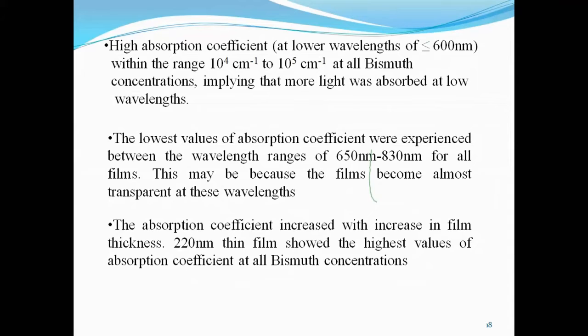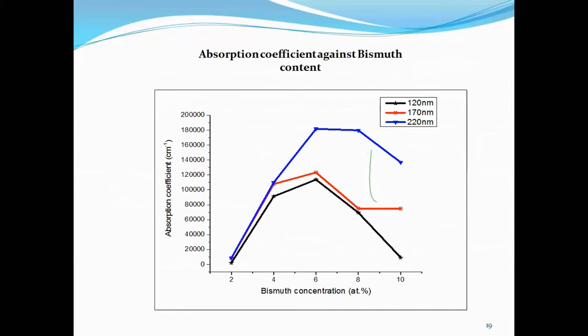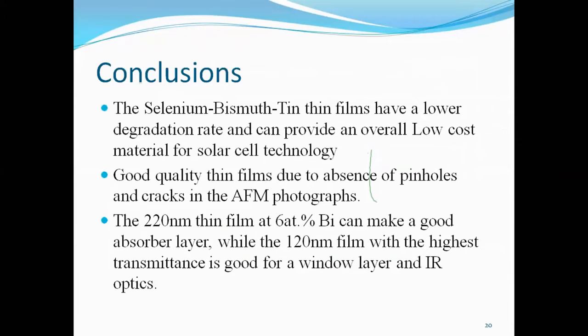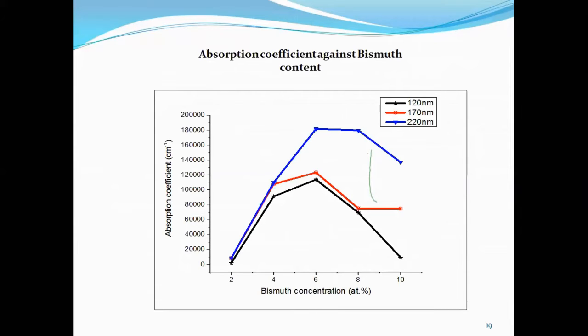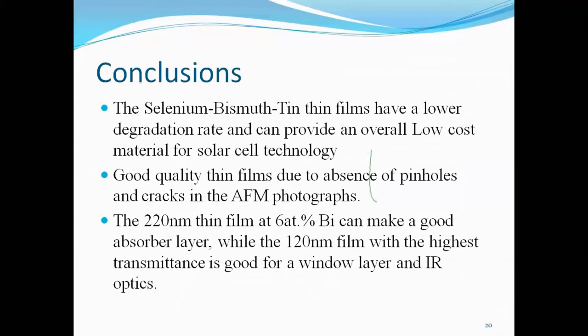Now, we used these graphs of absorption coefficient against wavelength to obtain other values, which we used to plot the next graph, this one, to tell us how the thickness affects the absorption coefficient. And you can see the 220 nm thin film is showing the highest absorption coefficient at all bismuth concentration. You can see on the x-axis we have the bismuth concentration, all of them, but the 220 nm thin film has always shown the highest. So this simply tells us that the thicker the film, the higher the absorption coefficient.